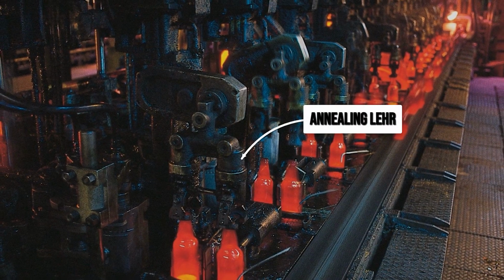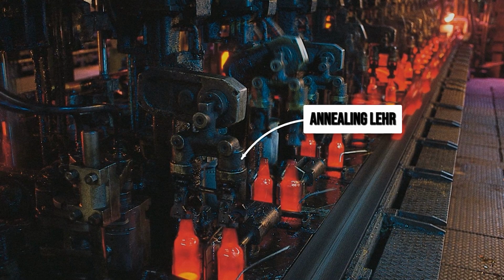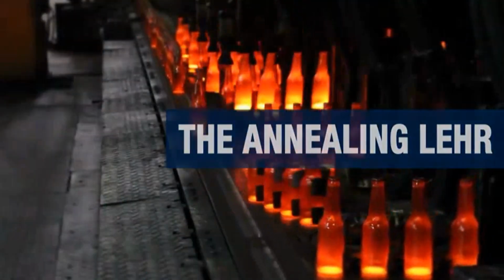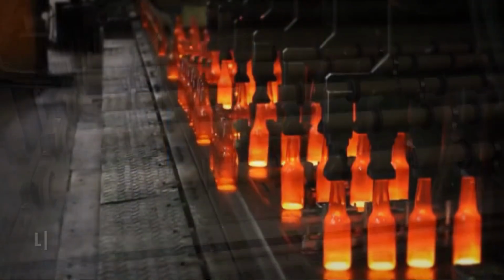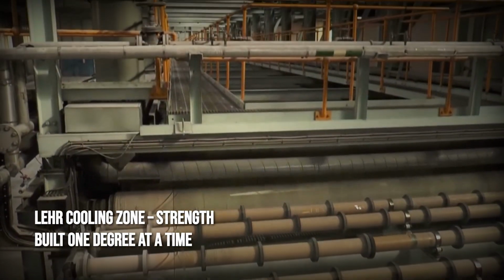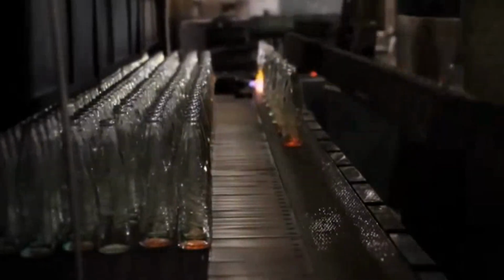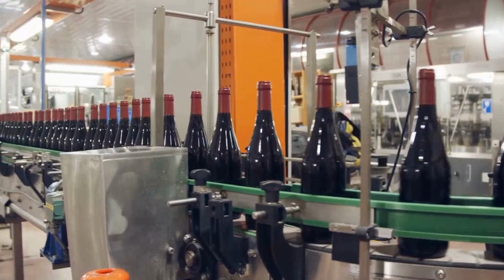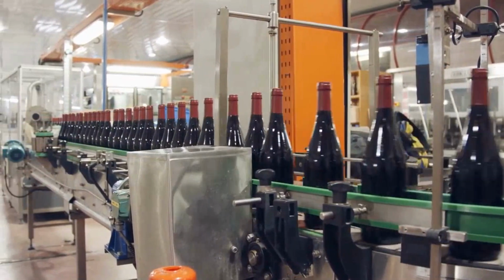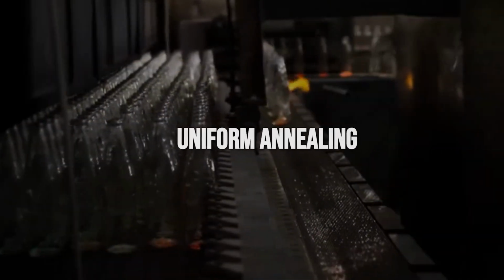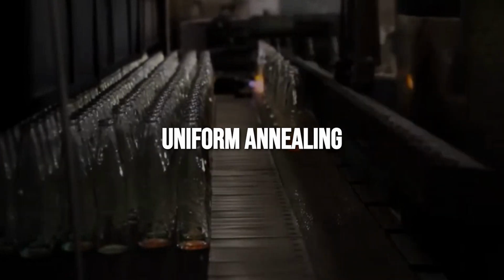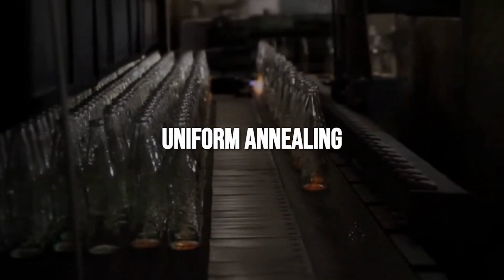Freshly formed glass, still warm from the shaping lines, enters the annealing lehr, a tunnel stretching the length of a freight train. Here, the temperature drops in carefully measured steps, sometimes over several hours, depending on the thickness of the glass. This slow, controlled cooling relieves internal stresses that could cause spontaneous cracks or shattering down the line. Conveyor belts move each sheet or bottle at a steady pace, ensuring every piece experiences the same gentle gradient from red hot to room temperature.